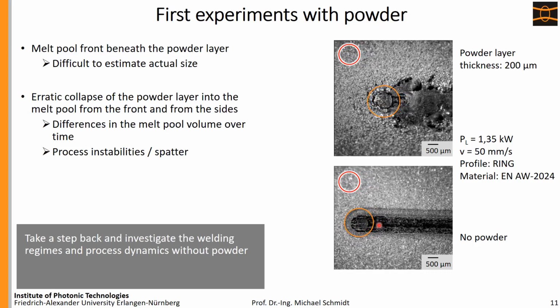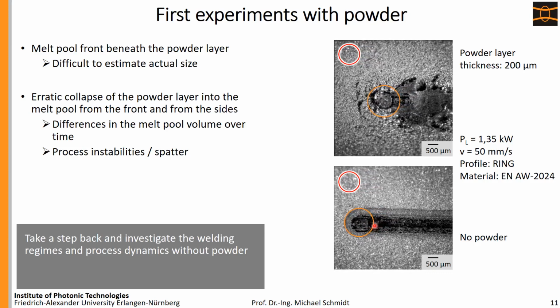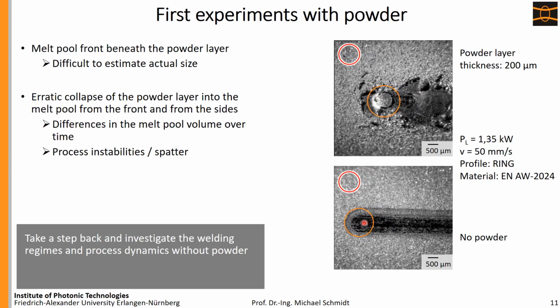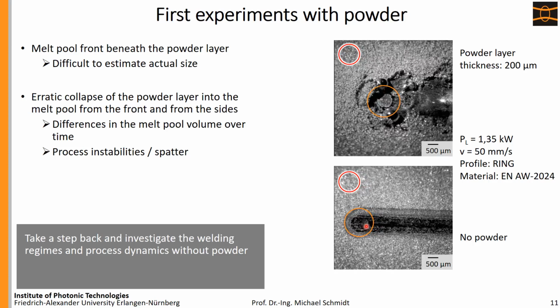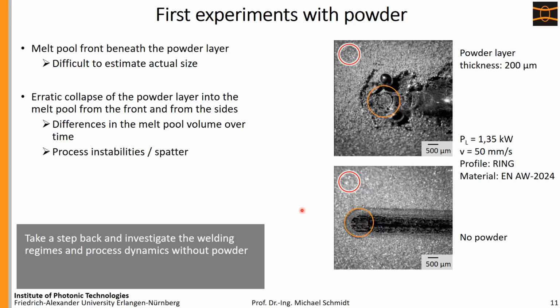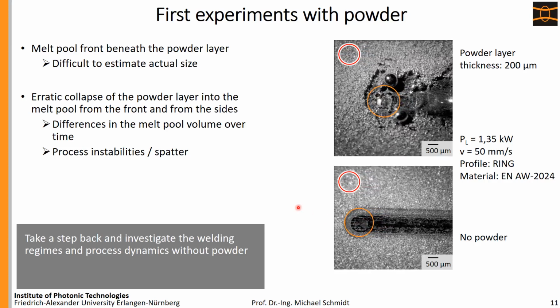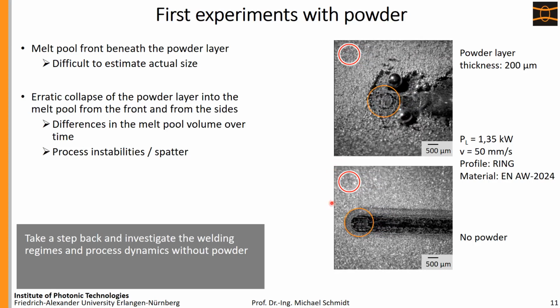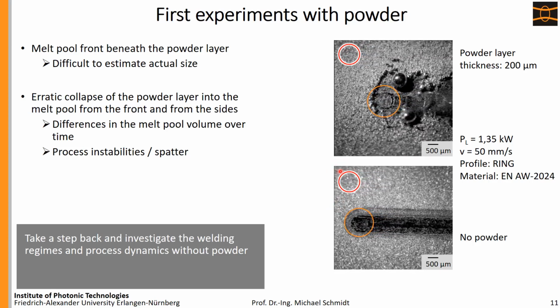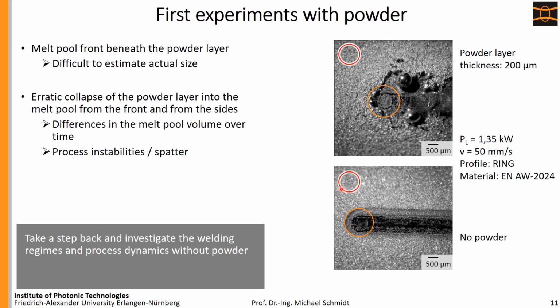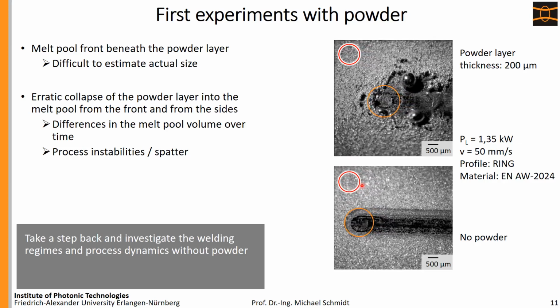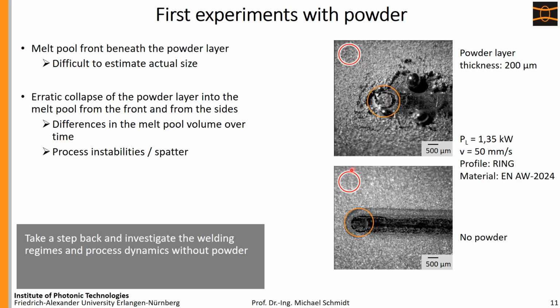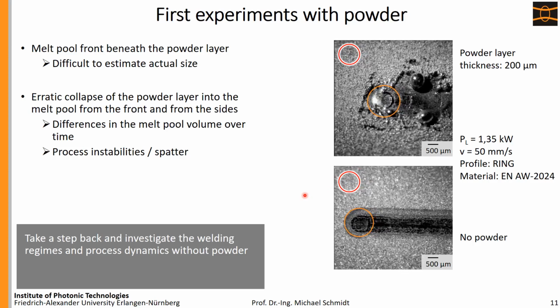The dark black areas here show that we broke the oxide layer and we had molten. We really were able to melt the oxide. And here it's quite easy to see which area is molten and which not. What you already can see from both ones, it seems with a ring shape, this is a real calm process, so no big process dynamics here, no spatters at all. I will come back to that one later.